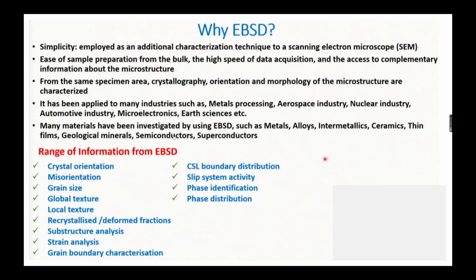By using EBSD, you can get a range of information, like your crystal orientation, micro misorientation, grain size, global texture, local texture, recrystallized and deformed fractions, strain analysis, substructure analysis, grain boundary characterization, CSL boundary distribution, slip system activity, phase identification, and phase distribution. From EDS you can simply measure the percentage and presence of your elements, only that. But EBSD is something else. You can have a lot of information.